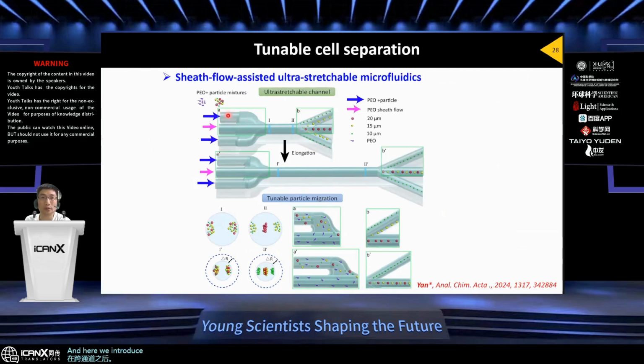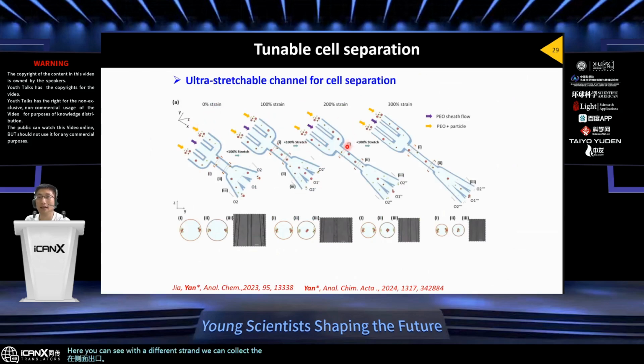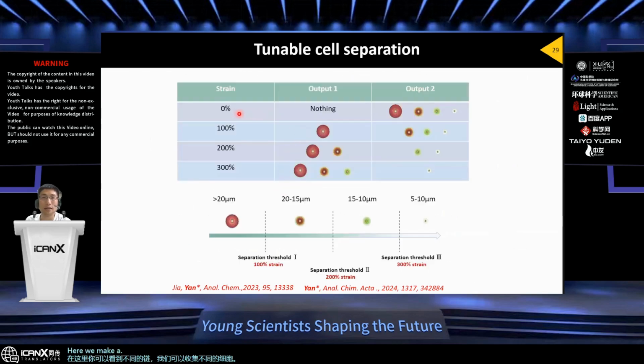And here we introduce the sheath flow into our channel, and the particles will be introduced from the side inlets, and the particles will be confined at the side walls of the channel. The large particles can migrate to the center, so they will exit from the middle outlet. The smaller particles will be collected from the side outlet. Here you can see with different strain, we can collect different cells. Here we make a summary. For example, without channel elongation, all the particles will pass through the side outlet. With 100% channel elongation, we can collect the large cells from the middle outlet, and we can collect the rest of the cells from the side outlet.